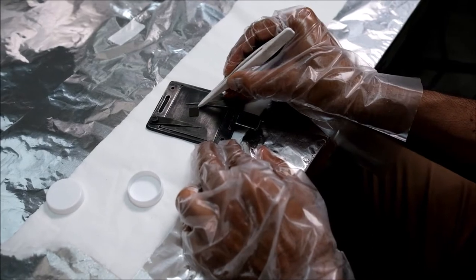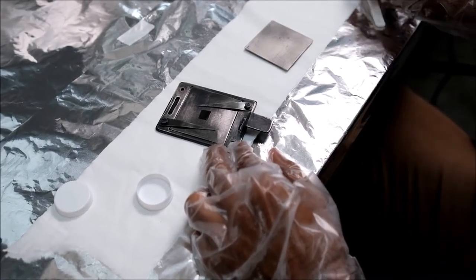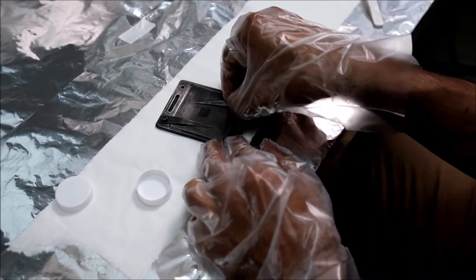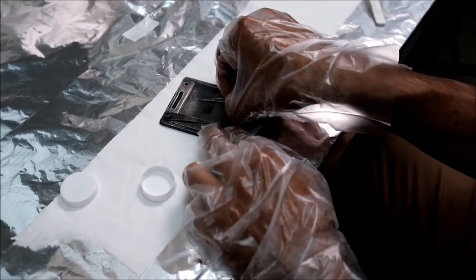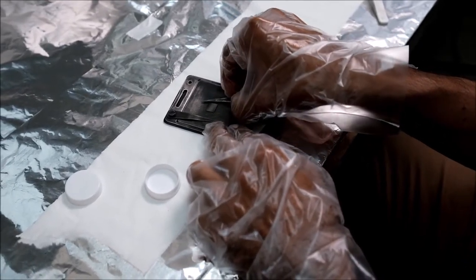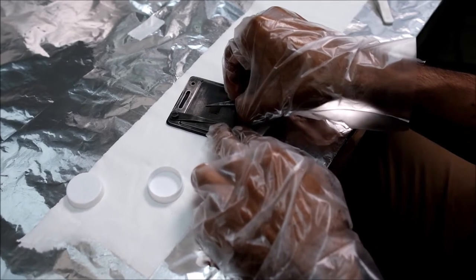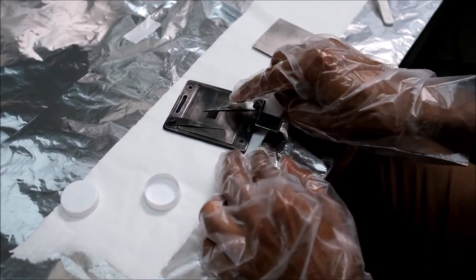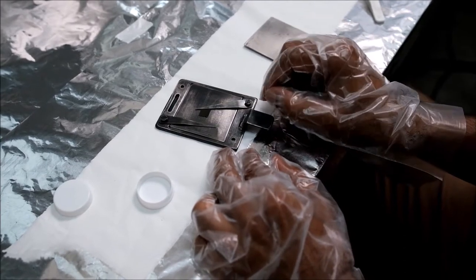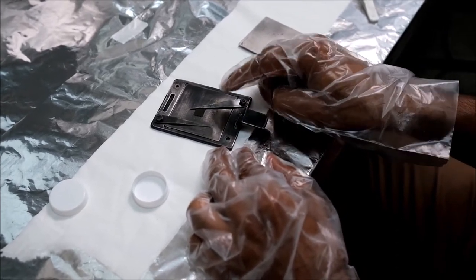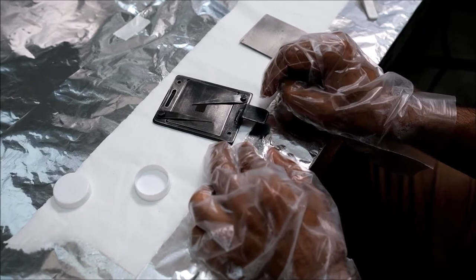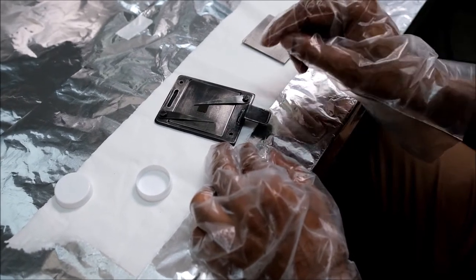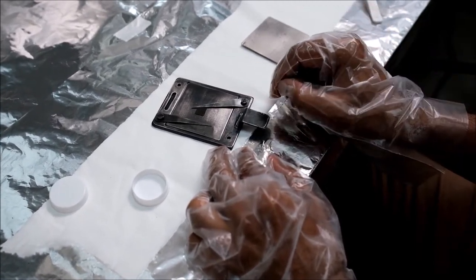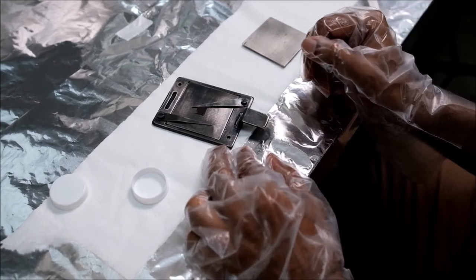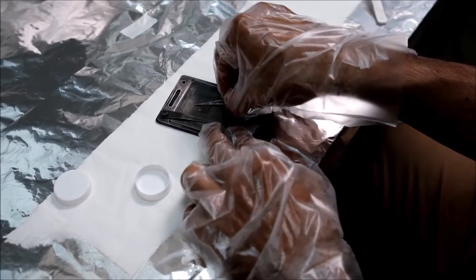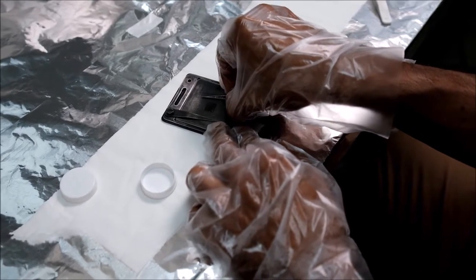Sometimes while depositing we may need to mask a certain part of the substrate. This can be done by this clip, so we can use the clip to attach and also to use as a mask. This way, there will be no deposition at the clipped part, and we can access the substrate. This is useful for a metallic substrate when we want to use it as a bottom electrode for electrical characterization. And also sometimes we may need to use a pattern deposition.